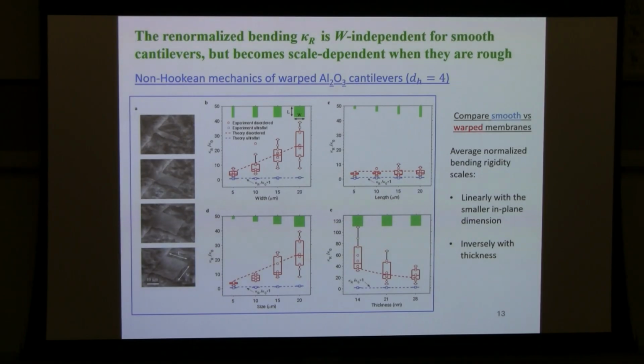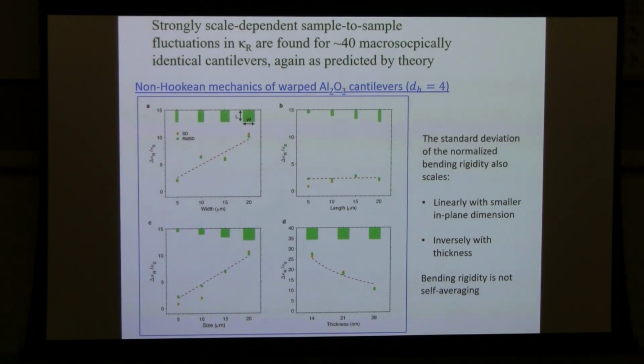Okay, so just a summary, they compare the smooth versus the warped membranes, and you get this linear dependence, and we get very large sample-to-sample fluctuations, which are predicted to grow linearly with distance as well. At least we have an example where, because of the out-of-plane flexural phonons, you better take Hooke's law, this venerable Hooke's law from 300 years ago, with a fairly large grain of salt.